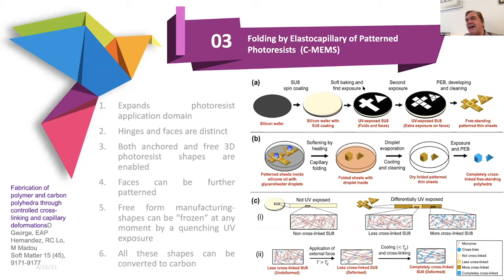Now, you can see that after a first exposure, I'm doing a second exposure, and that is key. In the second exposure, I can send more UV photons onto the planes, the faces, strengthening them and leaving the folds over here with one exposure only. The consequence is that the faces are stiffer and the folds are more flexible. So after developing and cleaning, I end up with these shapes that have much better distinguishing features than a plain PDMS sheet. Indeed, I have folds with a lower Young's modulus, so they can flex, they can flap, and I have faces that are stiffer and will not fold as easily as the folding hinges here.